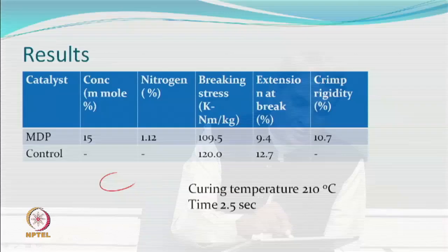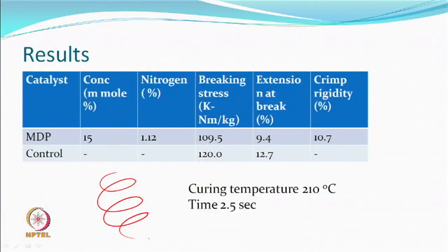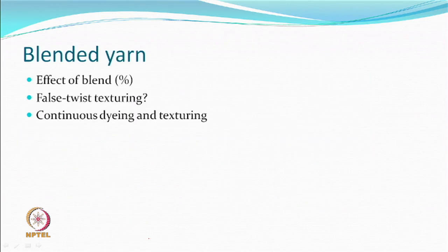So, you can measure nitrogen. So, some strength loss you can see from a control 120 to 109. Extension at break also reduces, and some crimpiness has been obtained. That means this material is now a textured yarn, which obviously has got helical structure, and you can do stretch and bulk both. So, if you have this process coming up to this level, one can use a blended yarn also, like polyester viscose, polyester cotton. If times are less, then you may think of false twist texturing. If possible, you can think of texturing and dyeing together, because there is a process called